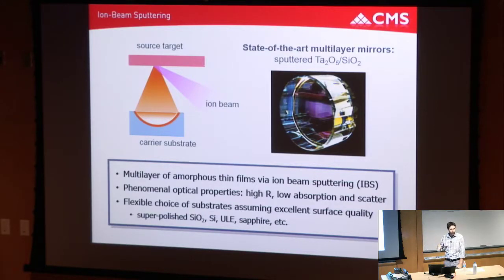These are interference coatings. So as I said, this is a multilayer of varying high and low index materials. This process was developed by Litton Industries for their ring laser gyroscope systems in the mid-1970s. You basically have a beam of noble gas ions, either argon or xenon, impinging on either a fully oxidized target or a metallic target in an oxidizing environment, and you put down amorphous thin films of metal oxides: tantalum pentoxide, hafnium oxide, silicon dioxide, aluminum oxide, etc.